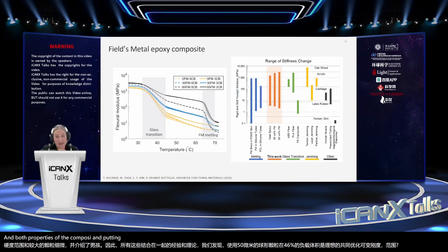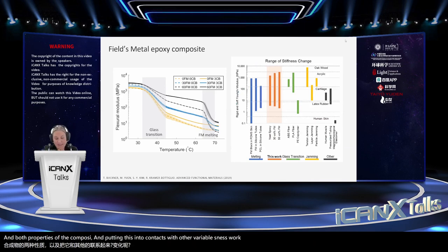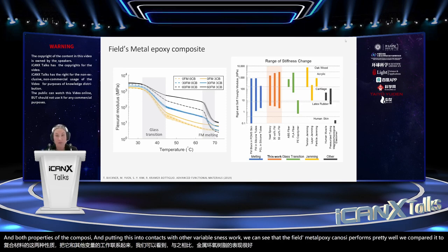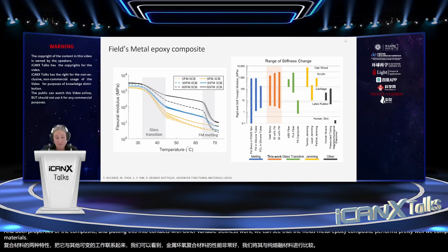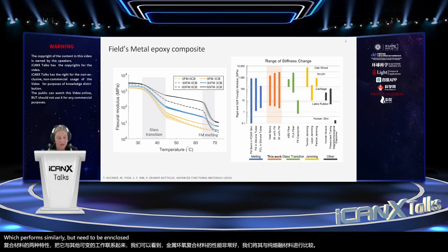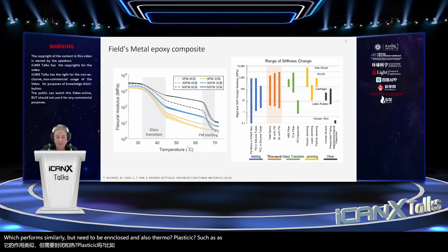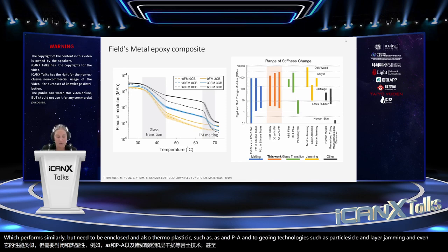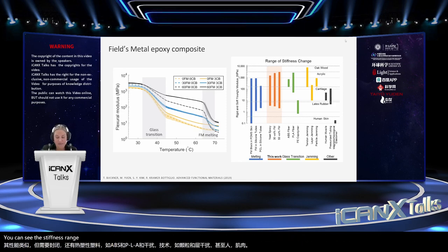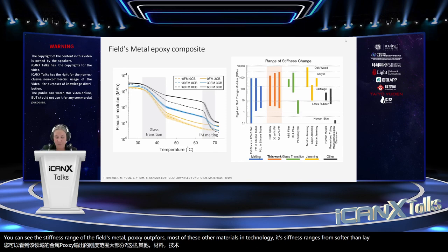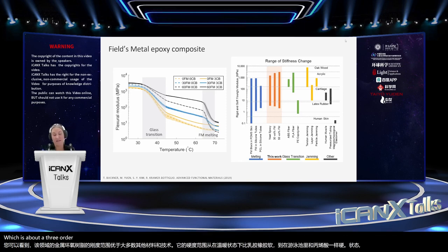And putting this into context with other variable stiffness work, we can see that the Fields metal epoxy composite performs pretty well. We compared it to purely melting materials, which perform similarly but need to be enclosed, and also thermoplastics such as ABS and PLA, and to jamming technologies such as particle and layer jamming, and even human muscle. You can see that the stiffness range of the Fields metal epoxy outperforms most of these other materials and technologies. Its stiffness ranges from softer than latex rubber in the warm state to about as hard as acrylic in the cool state, which is about a 3-order of magnitude stiffness range.